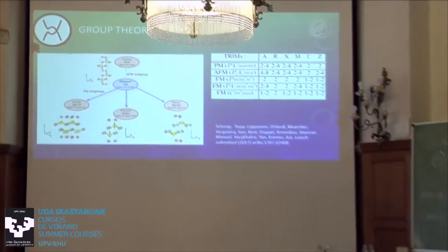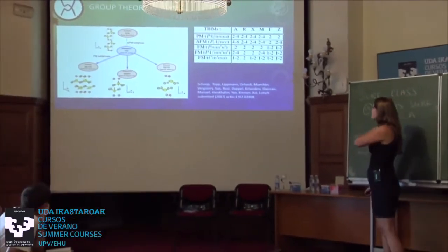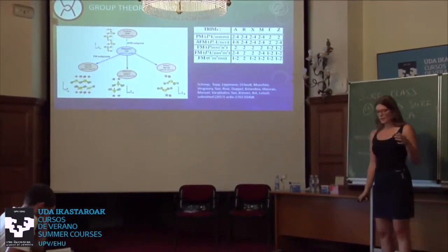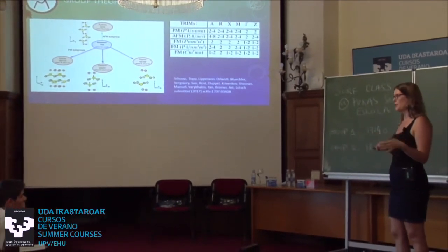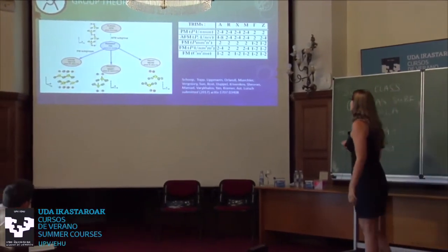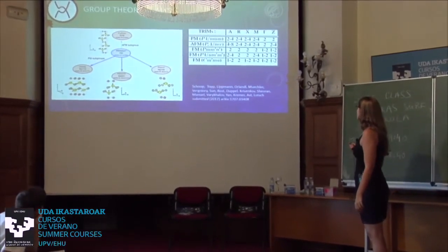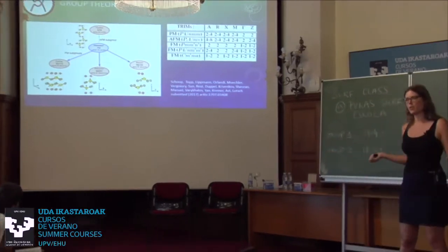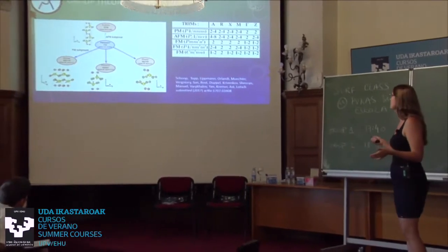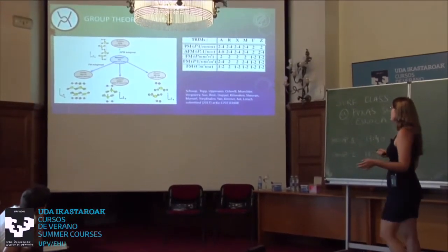This was done with Maia here, and she did a really nice job with a group theory analysis where she looked at the high symmetry points and looked at what the forced degeneracies do in each of those magnetic phases. So you can see, this was the paramagnetic phase, and like in zirconium silicon sulfide, we have the possibilities of fourfold degeneracies at X that I discussed before, but also at the other points. And then if you add magnetism, you change a lot of those degeneracies. So there's lots of splitting. You can have only twofolds here in the ferromagnetic cases.